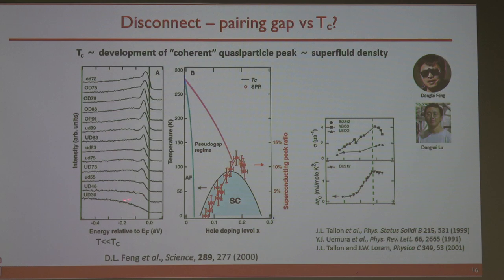What we plot is the strength of the quasi-particle peak as a function of doping. You see it correlates with TC and turns around at 19%. Remember that in the year 2000, the quantum critical point at 19% was not very clear 25 years ago. But the data already suggests something here.